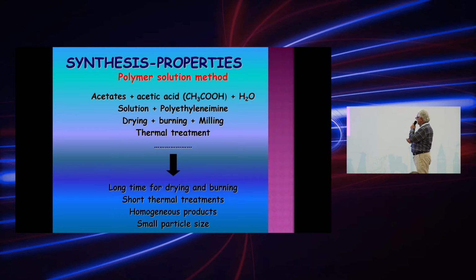In this technique, acetic acid and distilled water are used. Then after obtaining the solution, we add polyethylenimine in order to polymerize the solution, then drying, burning and milling. Then thermal treatment is applied. The disadvantage of this polymerized solution is only the long time for drying and burning. The other aspects are an advantage compared to other techniques: short thermal treatments, homogeneous products, and small particle size are obtained.